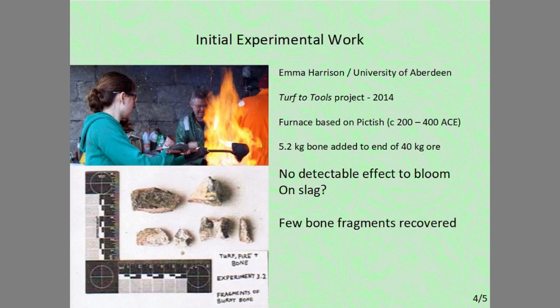Emma would later take part of the top of the bloom and subject it to laboratory analysis, and the discovery was there was no noticeable effect. There was some change in the composition of slag during the very end sequence of the smelt, probably attributed to the calcium from the bone. Importantly, very few bone fragments were actually recovered.